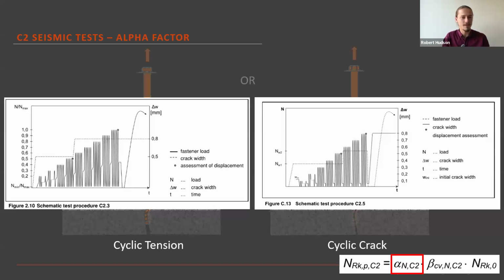If you have a crack width that's a little bit more than 0.8 mm, you get a significant reduction in capacity. If it's a little bit less than 0.8 mm, you get a significant increase in capacity. And similarly for the number of cycles, especially at maximum crack width, if you add more cycles to that test, your capacity drops. And if you reduce the number of cycles, your anchor capacity increases significantly. And this will be important for something I'll mention later in the presentation. But these values, where they sit, really is what is defining our C2 capacities. And especially, it's really this test.